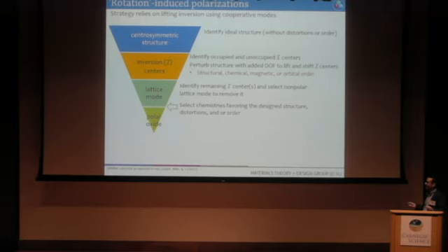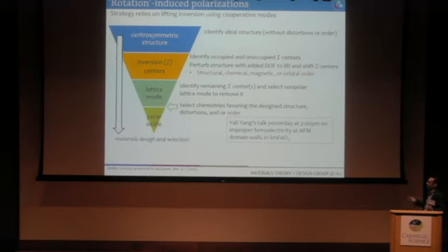Okay, this idea of adding order was discussed yesterday in samarium ferrite, where we saw that improper ferroelectricity can be induced by antiferromagnetic domain walls. So that antiferromagnetic ordering was an added feature in the crystal structure that in combination with the structural distortions lifts inversion symmetry. The strategy is all the same. It's just whatever type of order, long-range order, you're most comfortable with. And then with this design strategy, you can find new polar oxides. So this is schematically what's happening.